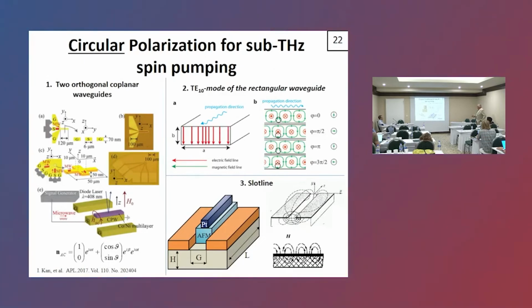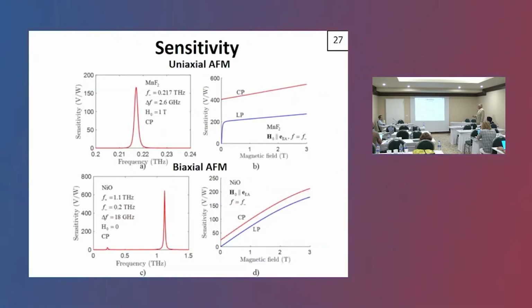It is very important to understand that you can get a good receiver in the case when the signal is circularly polarized, and you will need to construct the antenna in a specific way to get the response if the signal is linearly polarized. And the calculations show that for a linearly polarized signal, if you are not using the external bias magnetic field, you will not be able to receive anything in the uniaxial antiferromagnet. And you will need a biaxial antiferromagnet if you want to receive a linearly polarized signal. Circularly polarized signals can be easily received with a good sensitivity.